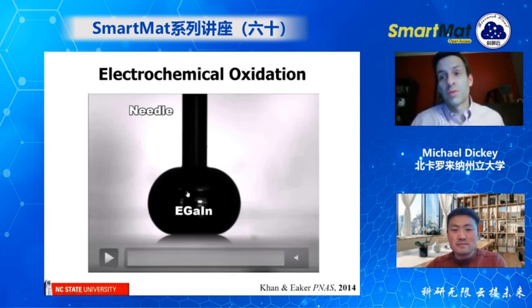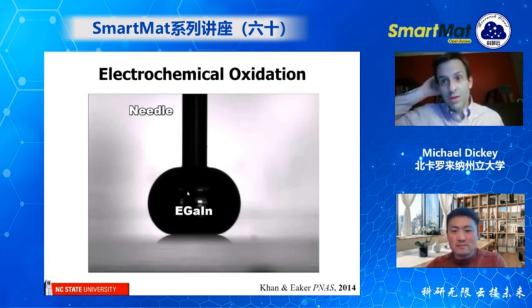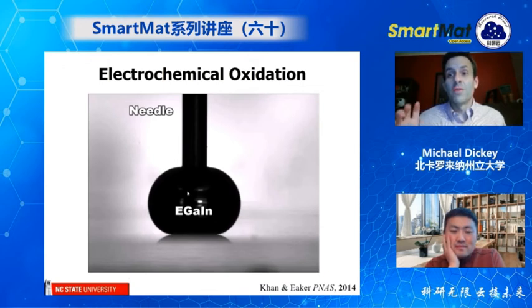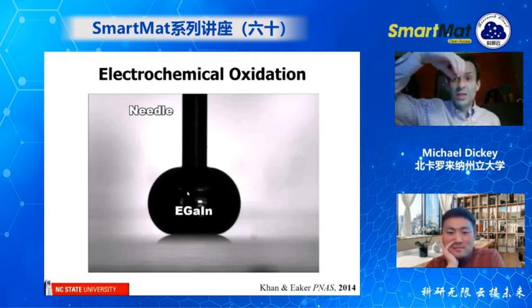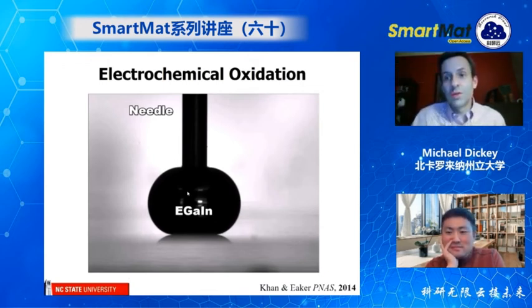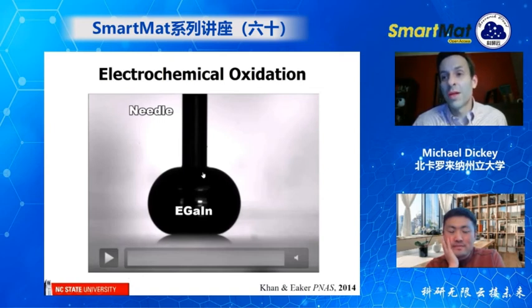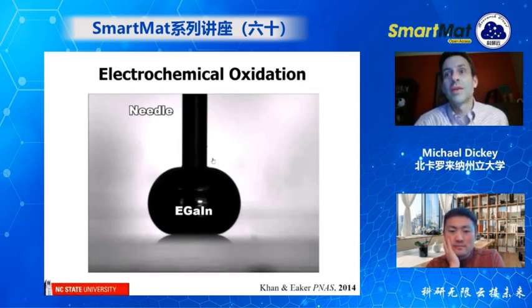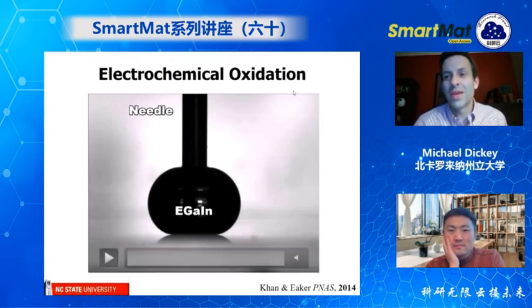In the case of liquid metals, they have the largest surface tension of any liquid. So if you want a small change in contact angle, you need to apply 100, 200, 300 volts, hundreds of volts. Here, we're applying 1 volt. And the counter electrode is not the substrate. The counter electrode is up here. You can't see it. And so this is not an effect of electric field.